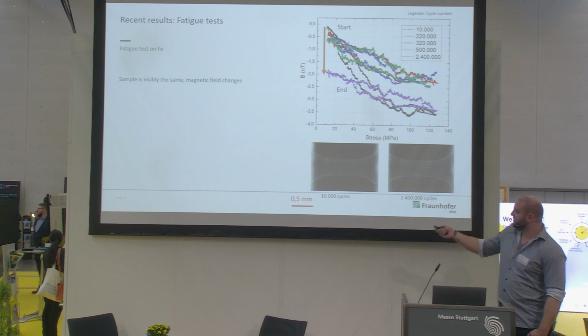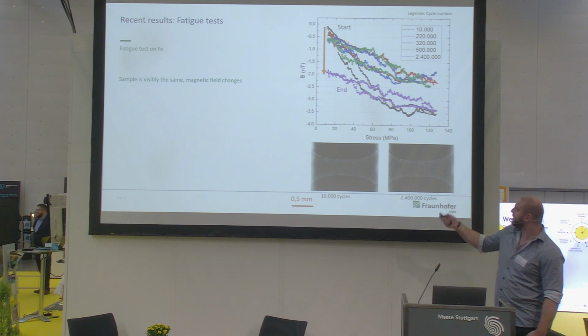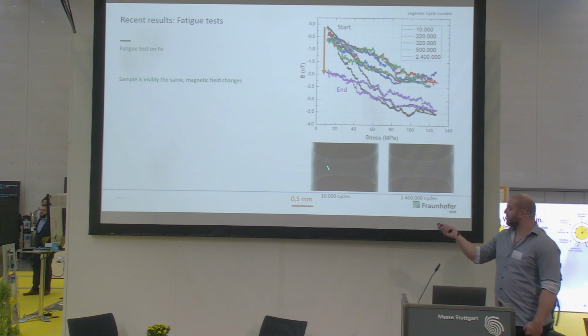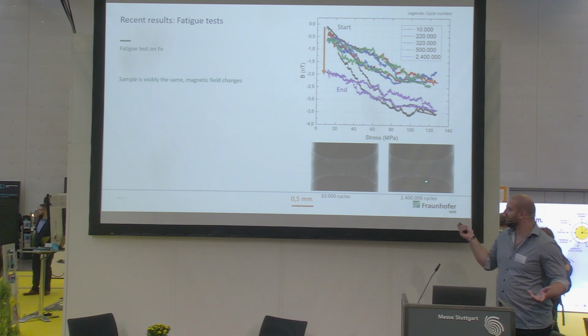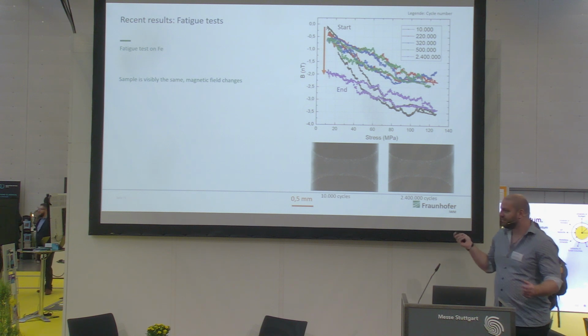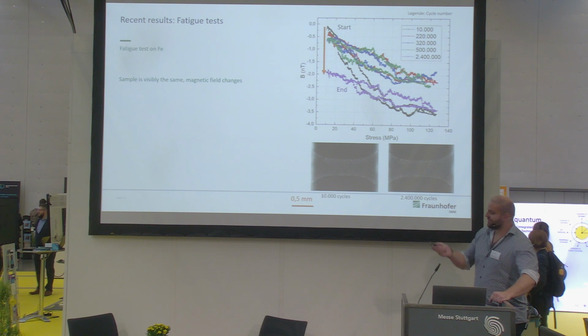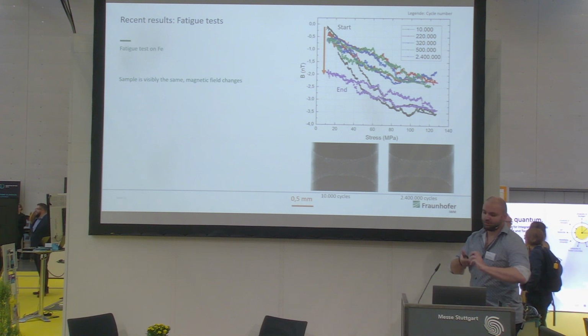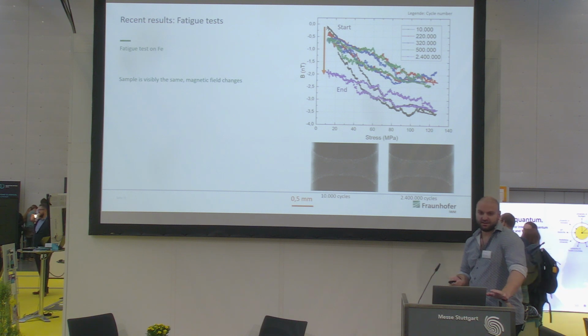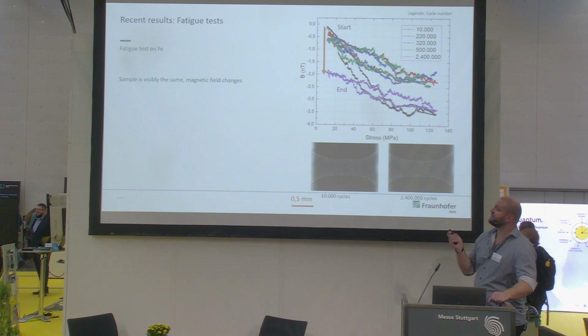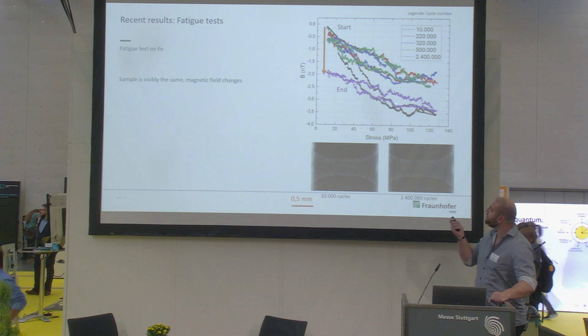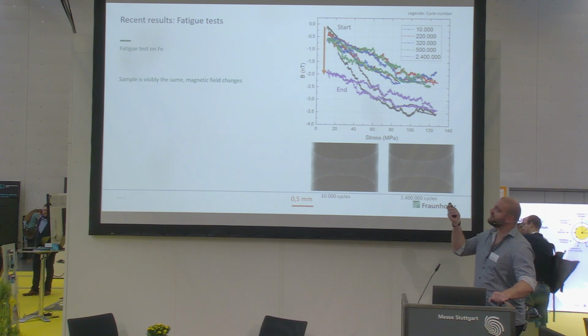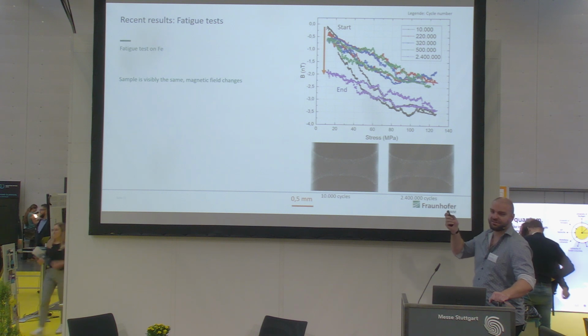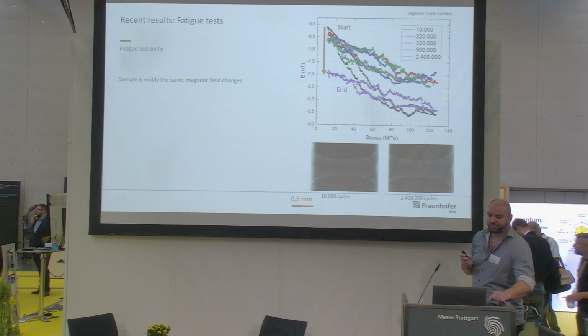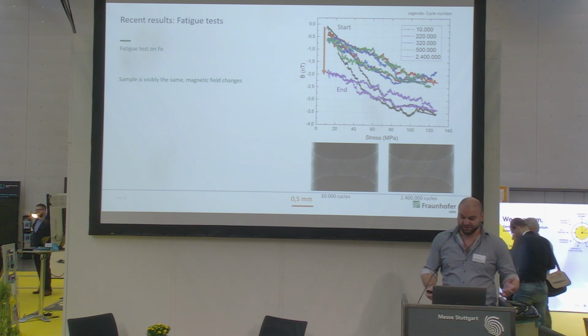On the bottom, you can see the sample. This is after 10,000 cycles, which corresponds here to the black curve. And we can see here after 2.5 million cycles, which corresponds to the purple curve. On the bottom row, which is macroscopic images of the sample, we see exactly nothing, which is also wanted, sort of. It just means that everything that happened in the material, like any fatigue process, any dislocation emission, whatever happened, is not visible yet in any measurement technique that we have. But the magnetic field is changing already. So we can see here from the black curve, it moves up to this level on top. It stays here for a while, and somewhere between 500,000 and 2.5 million cycles, the whole cycle shifts down. So the magnetic field is actually already changing, but we don't see it in the sample.